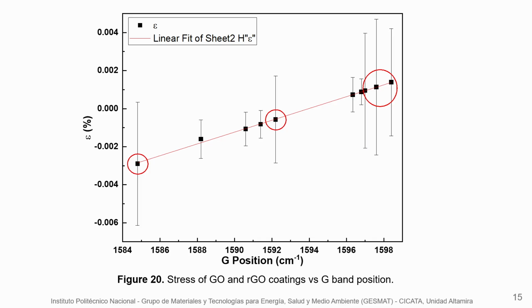Also, with the Raman data, we calculate the strain of all the samples using a baseline, the data of the graphene powders. We can see that the dispersed strain parameters against the G position of the samples show a positive slope. This is always attributed to polycrystalline graphenic material, which is according to the graphene oxide powders. Labeled in the red circle are the data for the samples with thermal treatment. We can see also that the error bars are very large, which shows the dispersion of the data, and that the thermal treatment samples do not have homogeneous properties.